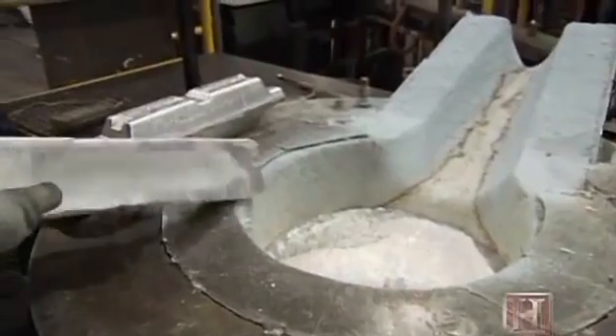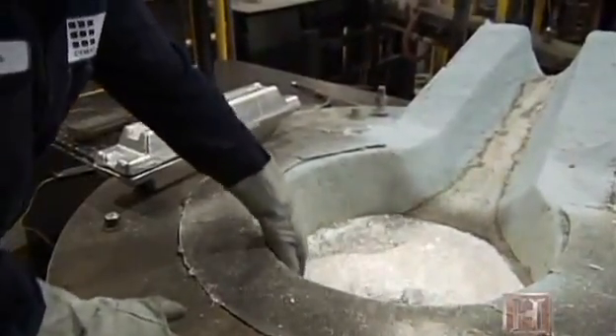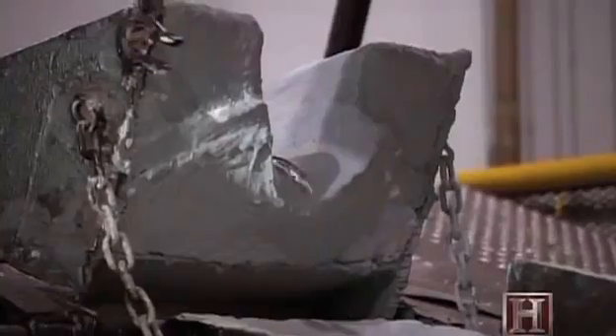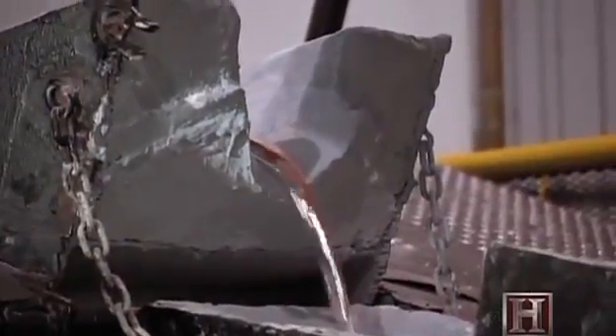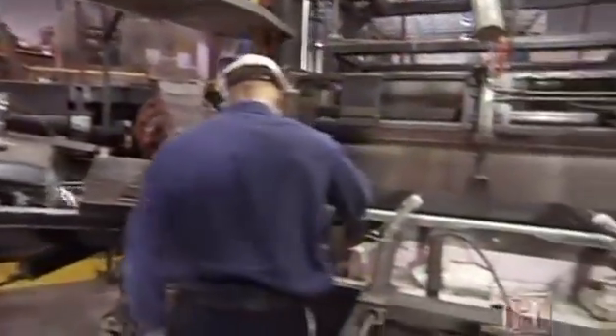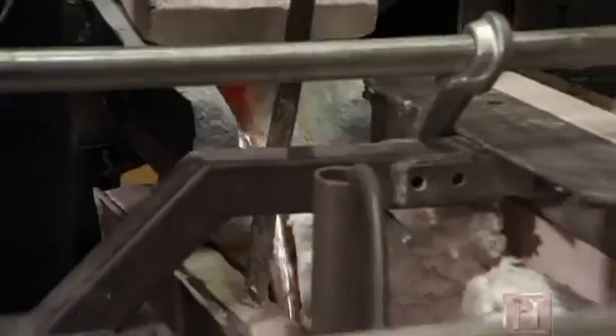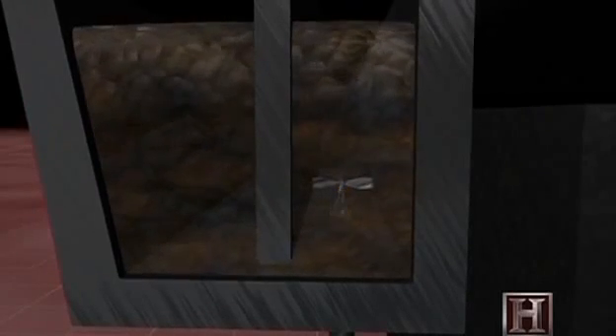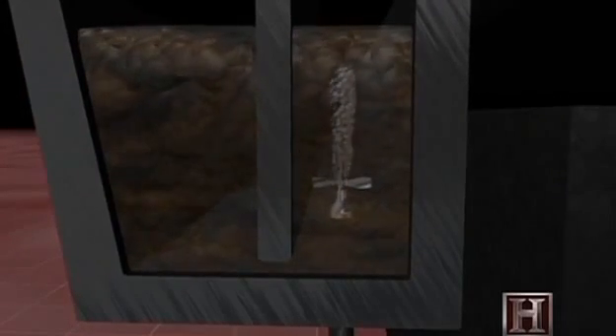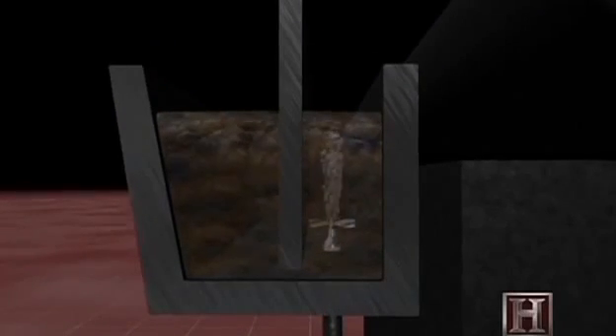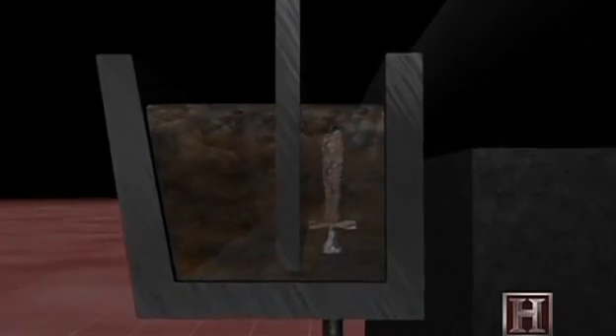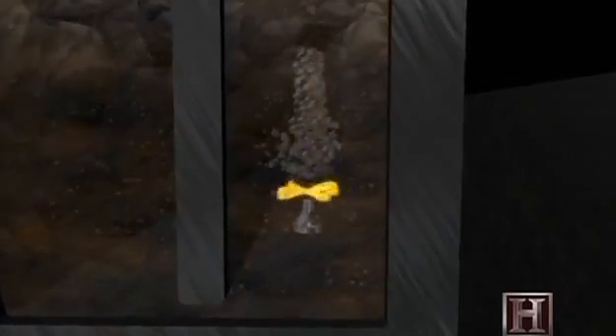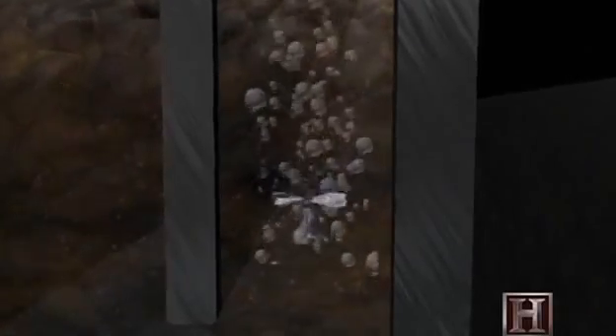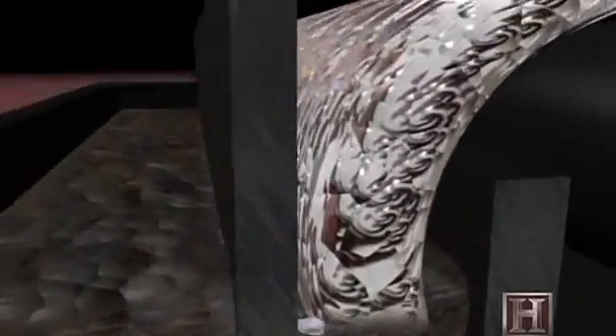Cymat begins its production process by melting down aluminum bars, already containing the ceramic particles. The furnace holding the materials spills a scalding stream into a channel, leading to a receptacle called the foaming box. Now it's time for the all-important air. Inside the foaming box, a nozzle injects air, creating bubbles in the molten concoction. More air creates a less dense and lighter final product. A propeller at the end of the nozzle keeps the ceramic particles evenly distributed. The bubbles rise, and as they reach the surface, begin to cool and harden.